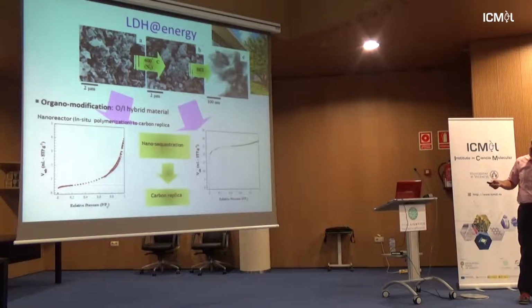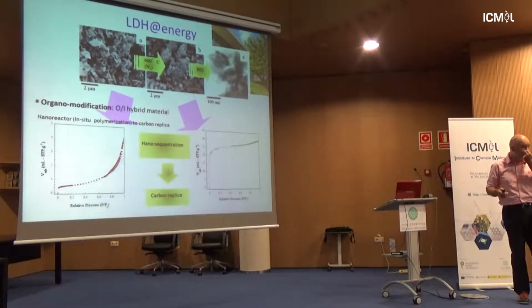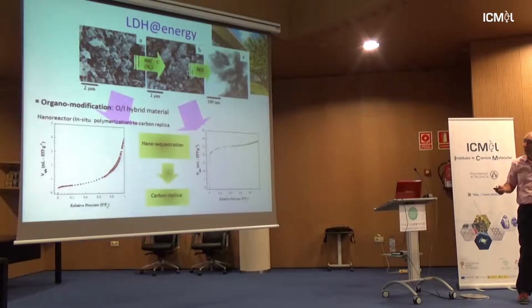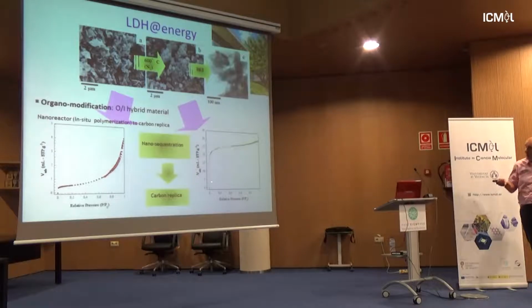That's a flake-like texture. You burn it under nitrogen or inert gas, because you don't want to get rid of all the carbon species under CO2, and you get some kind of a stone here. There is no porosity at first, and after you calcine at high temperature under nitrogen, you get microporosity. You can see it here by the steep rise of the adsorption at a low relative pressure, but you have nothing else after. You have no other porosity.